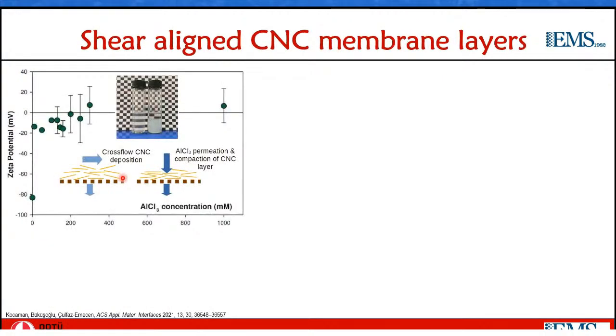So how to make this into a membrane? When we deposit the cellulose nanocrystals in cross-flow after a certain shear rate, we observe that they will align in the direction of the flow, and the higher the shear rate, the higher will be the extent of alignment. But if we would simply release the pressure of filtration, the deposit would simply go back into a suspension. So this needs to be stabilized on the surface.